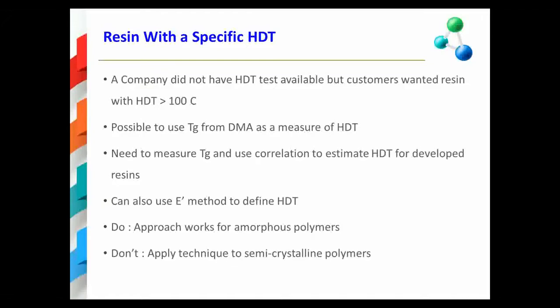However, after having provided that analysis, it certainly does need to be noted that the particular correlation between Tg and HDT is strictly valid only for amorphous polymers. A further discussion of semi-crystalline polymers will be provided in several slides.